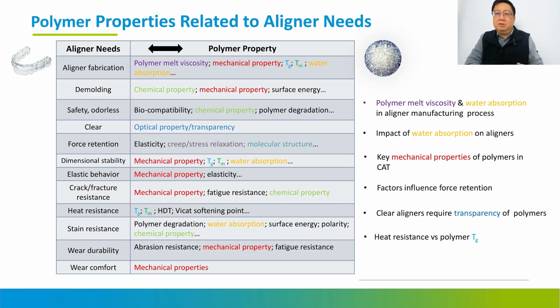In the old days, and even now, many countries still use a single layer of polyurethane or copolyester, which has very poor force retention. Normally in about 2 or 3 days they will drop more than 50%. The reason is that most of these materials have a lower glass transition temperature, and the oral temperature is about 37 degrees C, which means the polymer will decay in force because of this high humidity and high temperature.